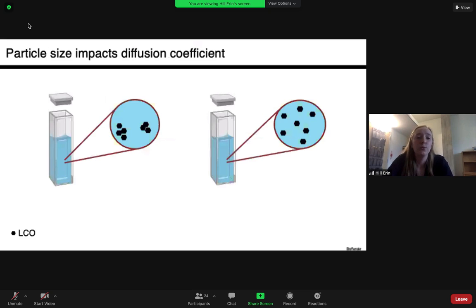We then turned to dynamic light scattering to see if our observations from the zeta potentials could be backed up by dispersion data. Dynamic light scattering works by exposing the sample to a monochromatic wave of light. The light scatters in all directions, depending on the size and shape of the molecule in solution. A detector picks up the scattered light, and depending on how the intensity of the scattered light changes, we can learn about the molecule's diffusion.